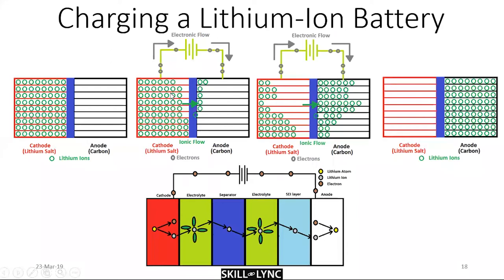As you keep the external circuit connected, all of the lithium atoms in the interstitial spaces move to the anode. Your lithium salt acts as the energy provider or lithium atom provider, and your carbon anode — which typically contains no lithium — gets filled with lithium atoms at the end of the process. This also explains why batteries swell up: the insertion of lithium atoms into carbon occupies the interstitial spaces, causing the carbon anode to swell by about 1 to 2%. As the cell degrades, that swelling can become quite significant.